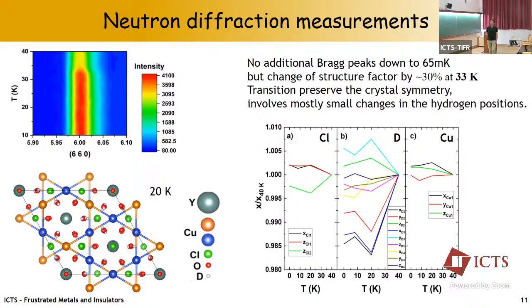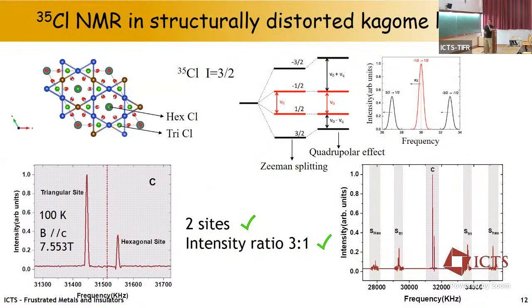So we wanted to have a closer, more local view on this problem, and we did chlorine NMR. So in the high temperature structure, we expect two chlorine sites. One sits at the center of the hexagon and one at the center of the triangles. And both chlorine sites are not in the plane of the coppers, they are out of the plane. So here is the central line, and we see two well-defined narrow peaks, which means well-defined structure, very little disorder, and with the ratio we expect for the two sites, so that's perfect.